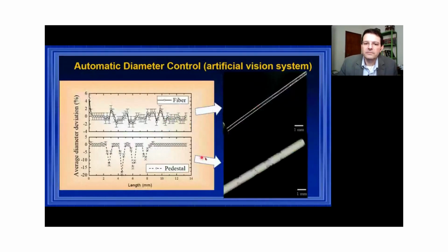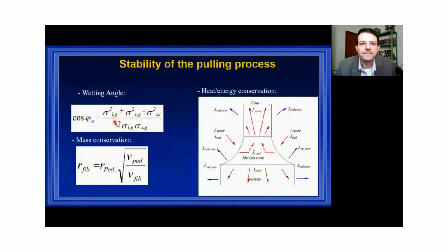So here, just to demonstrate the efficiency of this kind of diameter control system, we have a pedestal that is provoked with some fluctuations mechanically, and here's the fiber grown from those pedestals, and you can see that a 20% diameter fluctuation is reduced to less than 2%, even with a very strong out of equilibrium system, okay?